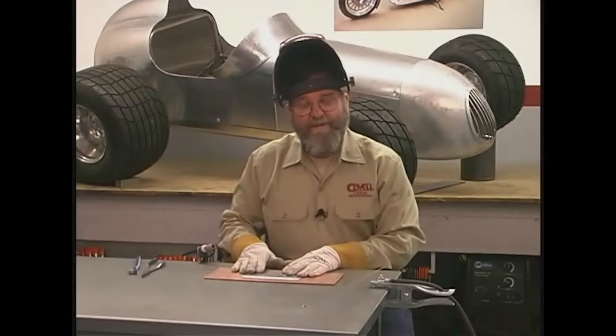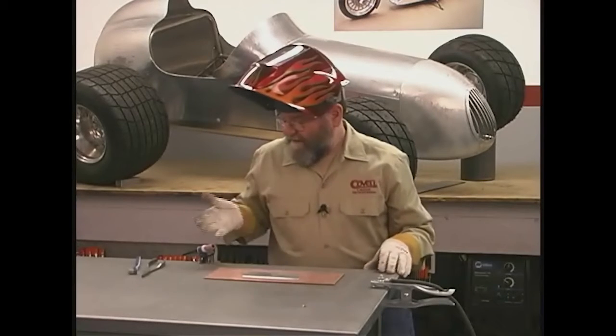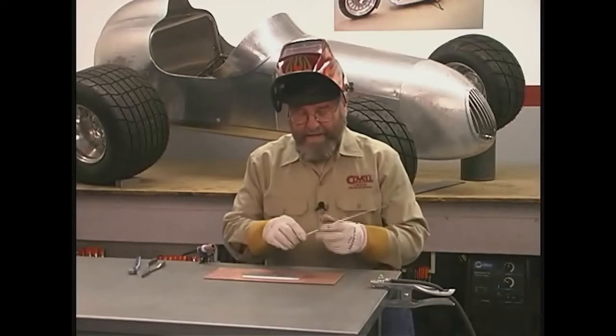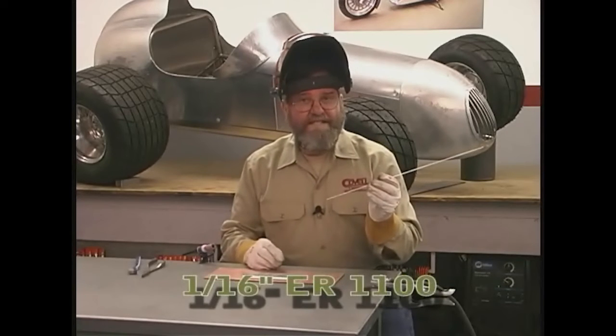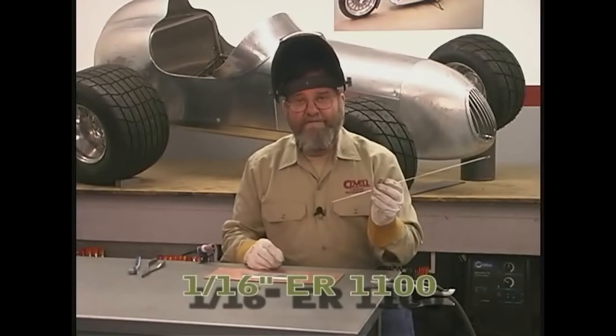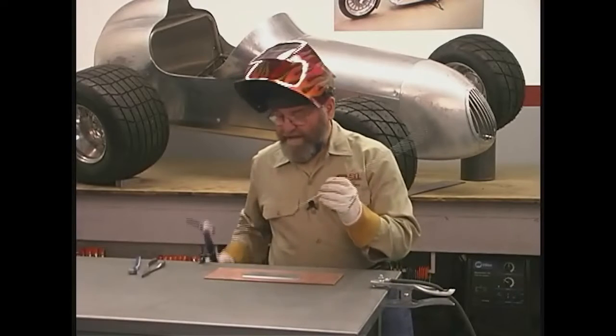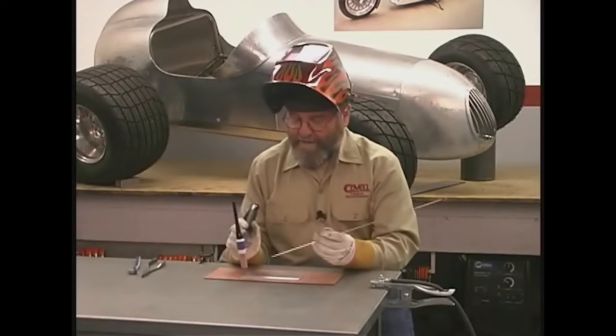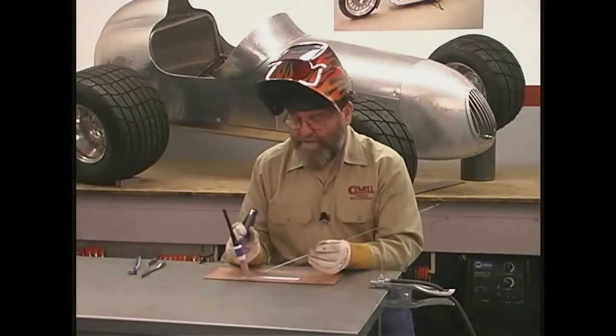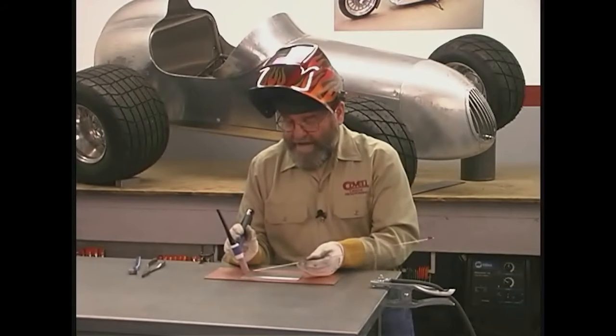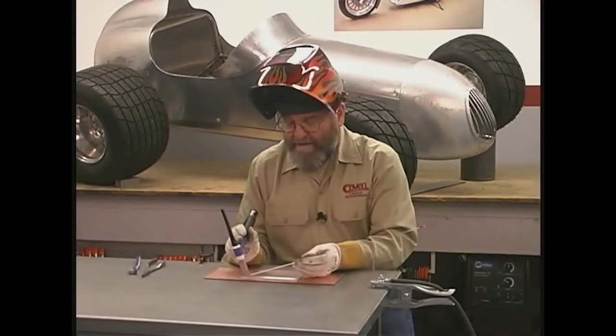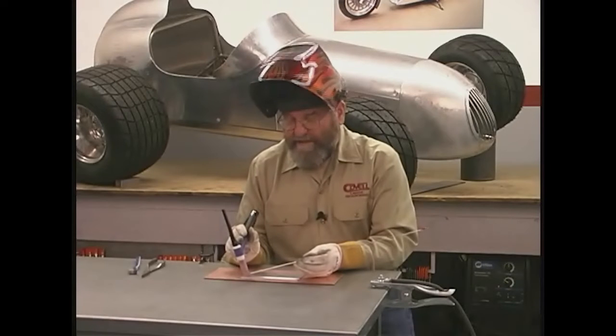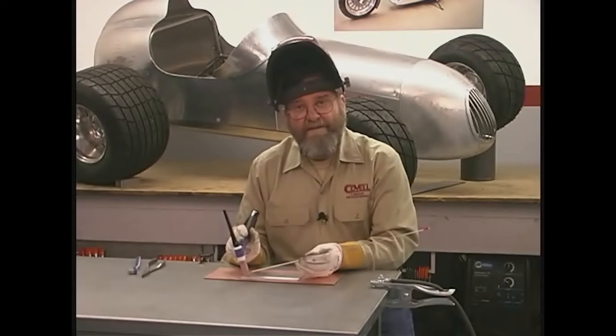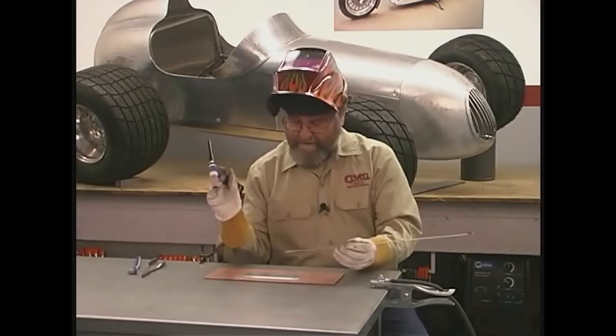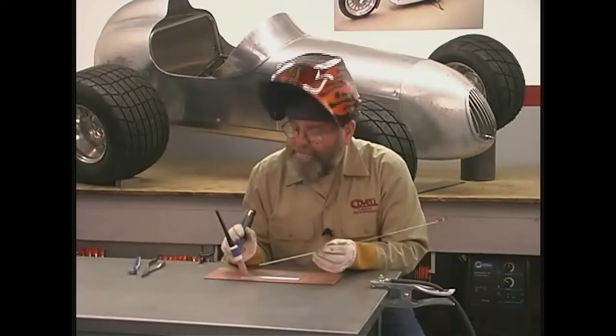Okay, now we're going to run a bead and add filler rod. The machine settings are the same, the tungsten setup is the same. The filler rod I'm using is 1/16 diameter, 1100 filler rod. So again, I'll get some pre-flow going with the torch, hold the torch at about 15 degrees off the vertical, and hold the rod at about a 15-degree angle off the work. So the angle between the rod and the torch is just about 90 degrees. Here we go.